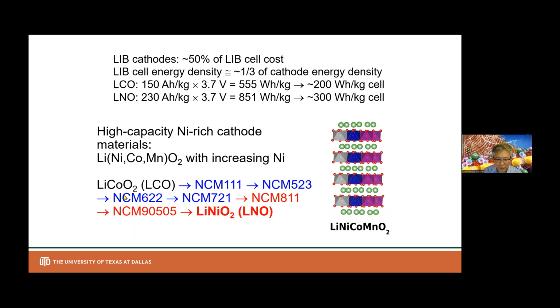This is where the current commercial product is, about 80% nickel, and some high nickel cathode materials have 90 or even 95% nickel concentration. At that nickel ratio in this layered metal oxide, the capacity is higher than 200 milliampere hour per gram, or ampere hour per kilogram. So we are increasing the capacity, but there are other issues accompanying this increasing density. Let's take a look at what those issues are and how we address those problems.